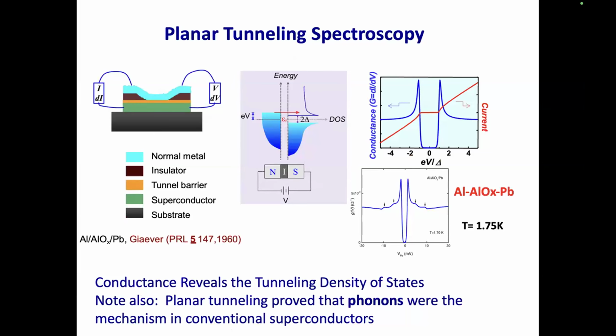You all know planar tunneling spectroscopy, and just to remind you, and I like to remind people on this, this here's just aluminum lead, and these little bumps here, these are the phonons. So one of the things we have in this material is that in any tunneling, these bumps in this aluminum lead are lead phonons. That was the indication that phonons were the pairing mechanism.